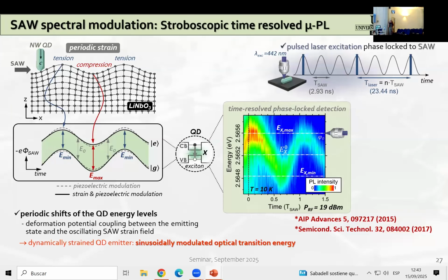The observed spectral changes can be attributed to the periodic shifts, as you can see here, of the quantum dot energy levels, which are induced by deformation potential coupling between this emitting state and the acoustically driven mechanical vibration or strain. In other words, as the acoustic wave propagates and couples to the nanowire, the embedded quantum dot is dynamically strained, and its transition energy is sinusoidally modulated so that it oscillates between a minimum and maximum value with respect to this equilibrium energy in the absence of the acoustic wave.